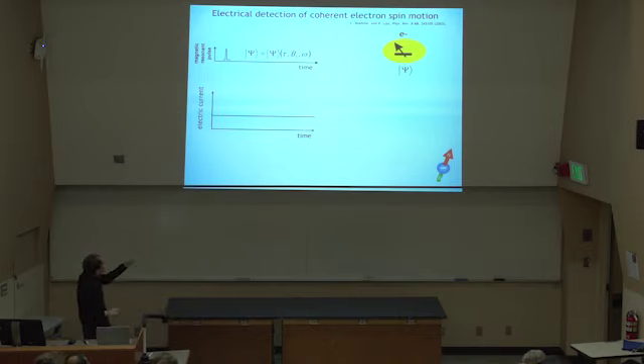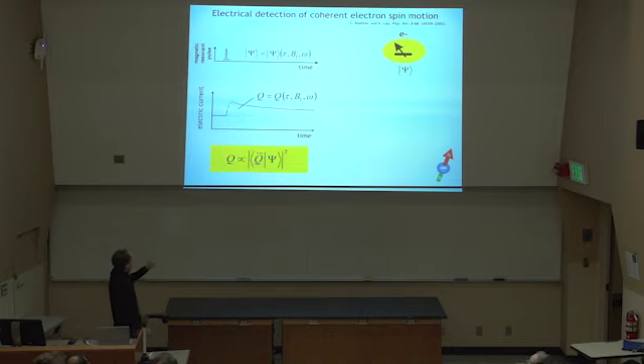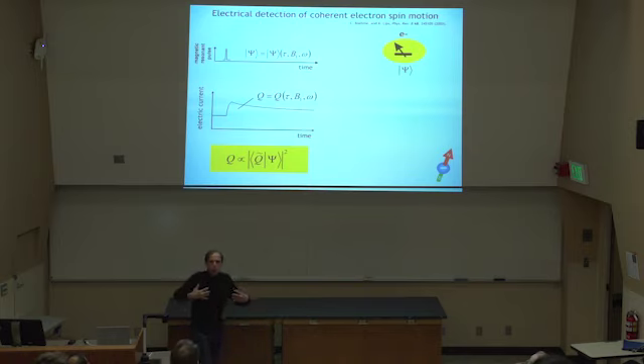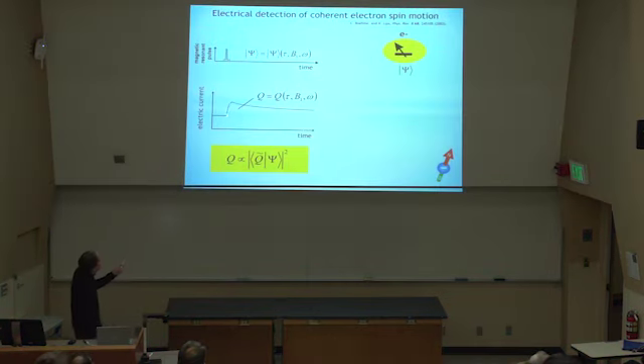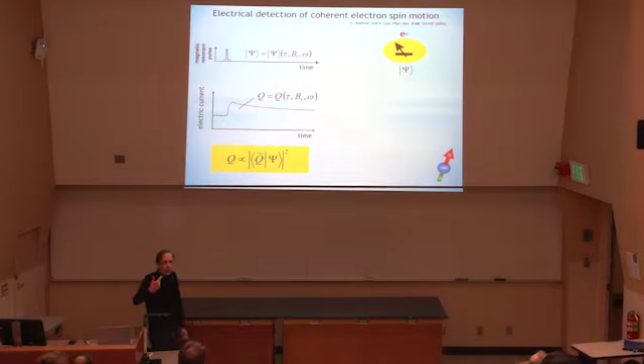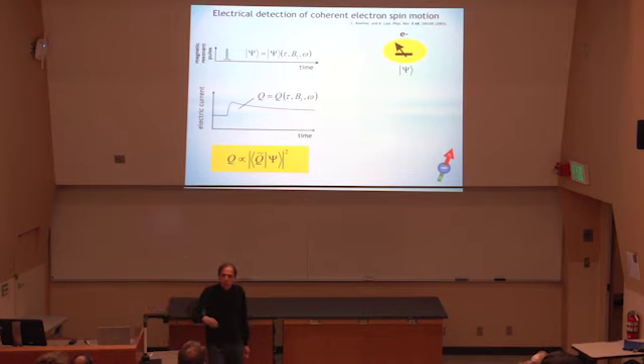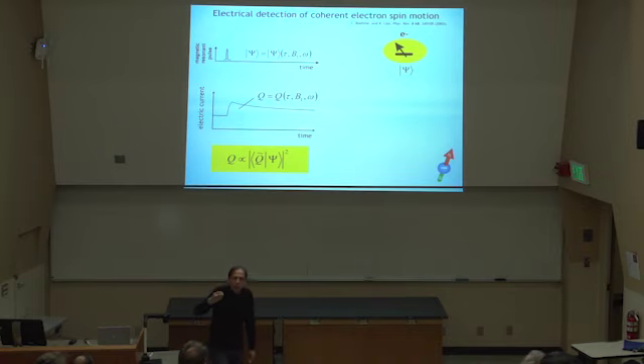And then we look at what our observables that we believe are governed by these processes do. And if the spin controls our observable, then of course there will be some change. If there's a change of current, you can record this. But then the current is, of course, influenced by a whole bunch of material parameters, dielectric relaxation time, meaning the built-in time constants of these materials, and the whole dynamics of how these spin manifolds govern electronic transitions, etc. And if you looked at the cartoons earlier, this can be complex because there are a lot of electronic transitions involved. So what we do then is, well, we observe this. And what you can do is just say, whatever the dynamics is, if we record this and then integrate the current change from the steady state, in other words, we count the charge, then this number of charges that we detect there indicates the change of the number of electronic transitions that took place due to that spin manipulation.